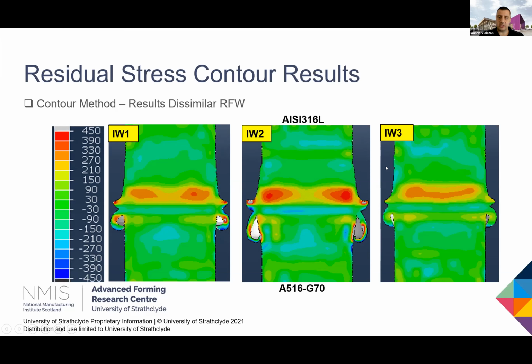What can be said is that we can probably balance the residual stress generation with the microstructure and try to tailor it for that specific need. It can become an issue if we machine out the flash, as we will be exposing those tensile stresses. In this specific case, we are measuring hoop residual stresses, but we can carry out supplementary measurements with XRD and hole drilling on this cut face and get the full 3D stress tensor. We have not done that for this specific application, but that is in our mind for the continuation work.